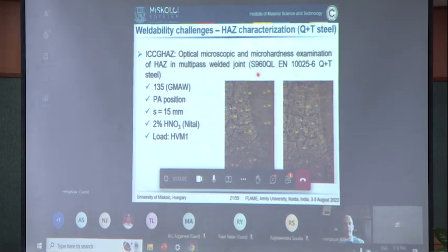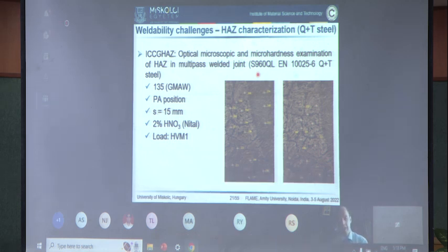Here you can see that in the case of the 960 quench and temper steel, we performed optical microscopic analysis and microhardness examination on a real welded joint, and we can identify that in this intercritical coarse-grained heat-affected zone, the inner part of the grains generally softens compared to the base material, having a hardness of maybe 200, 260, but at the original prior austenite grain boundaries, where these local brittle parts, mostly martensite-austenite parts, form, the hardness can go up even to 360, 330. So this shows the special characteristic of the microstructure, which should be the focus of the research.